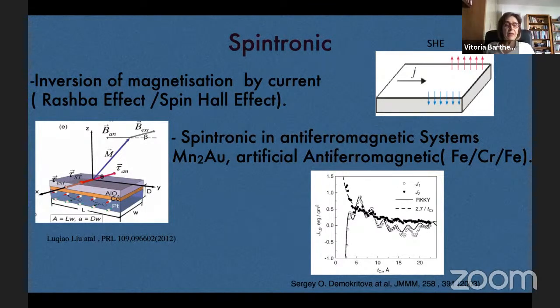In fact, this is at the surface of metallic non-magnetic materials like tantalum or platinum. When the current passes through this layer, a spin polarization is generated that causes a field that will turn the magnetization. This was shown by Liu in a ferromagnetic layer. And so we are thinking of using this in antiferromagnetic materials, because the attractiveness of antiferromagnets is that there is no stray field.